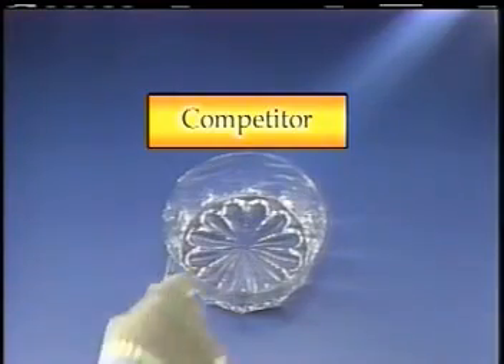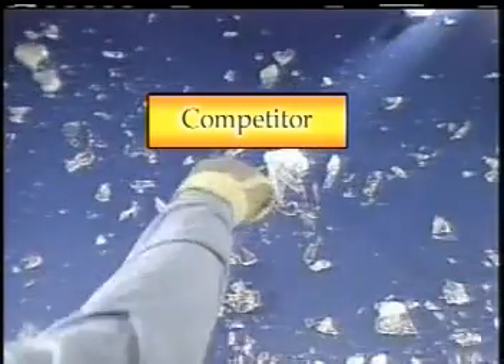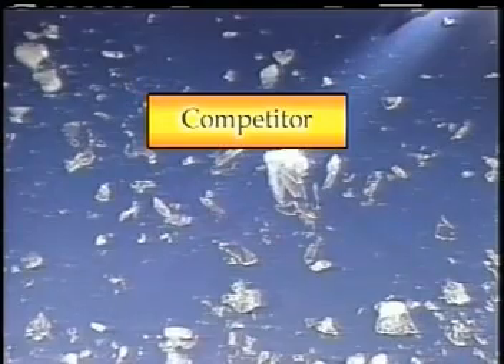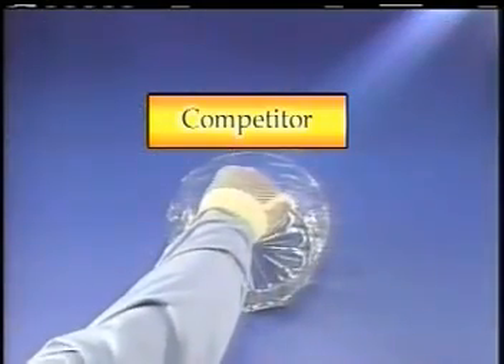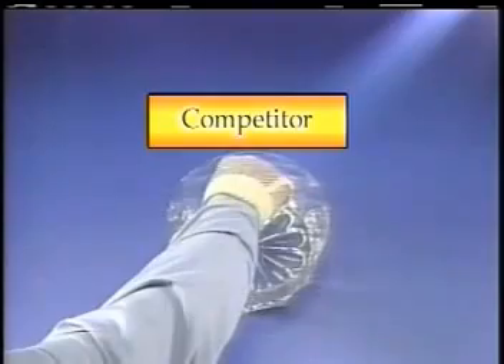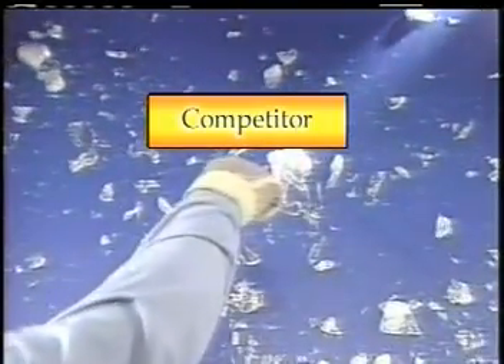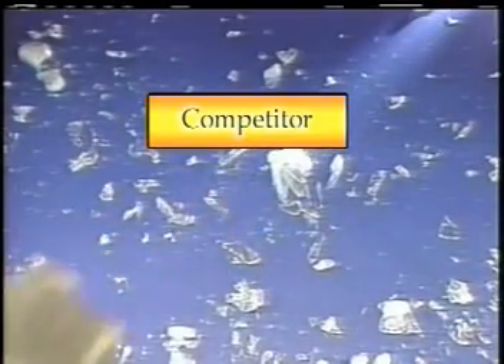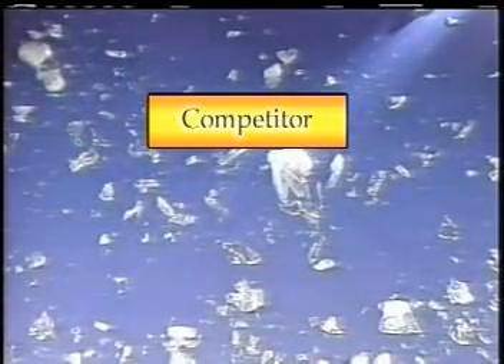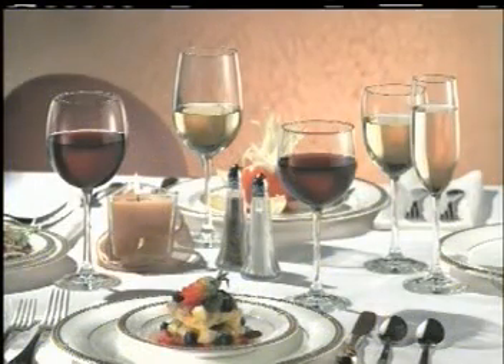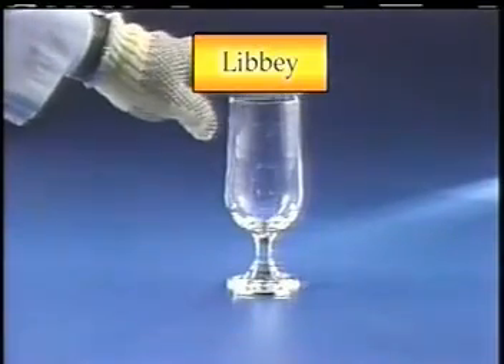However, watch while the bowl on the right breaks under an identical impact. As you can see, the breakage is much more violent, showering glass fragments over a much greater distance. And the pieces are smaller and harder to see. The reason is that the competition's bowl has been tempered to an unnecessarily high level. The dangers that this type of glassware poses to a food service operation are clear, which is why Libbey Glass has worked hard to balance the need for strength against the need for controlled breakage.